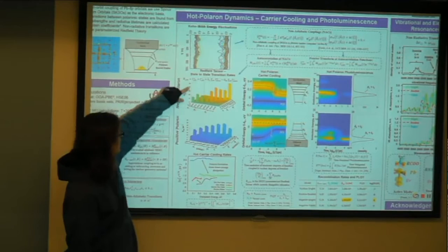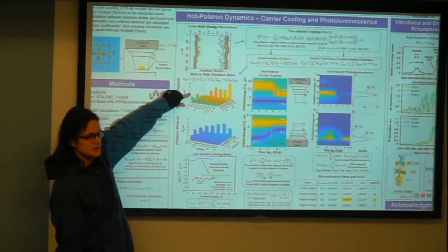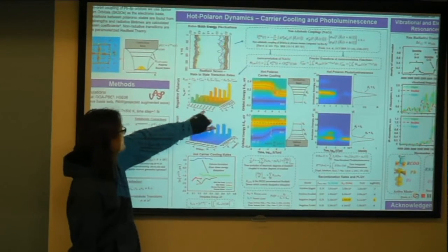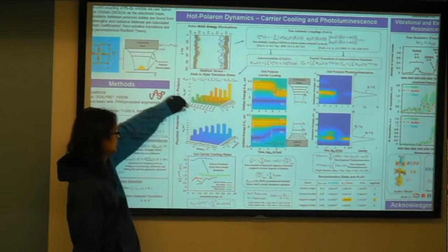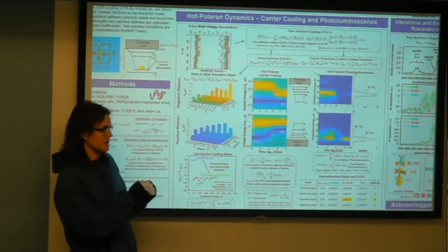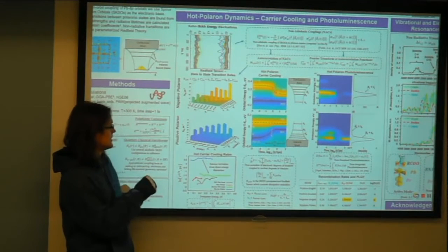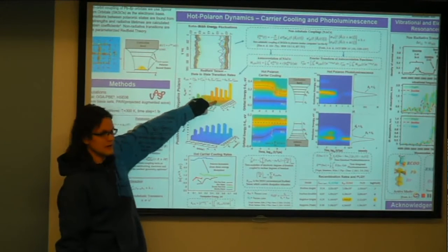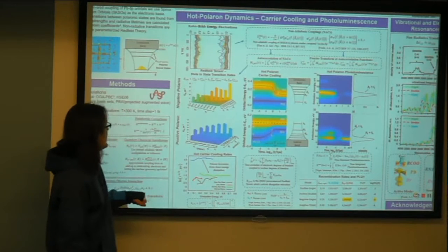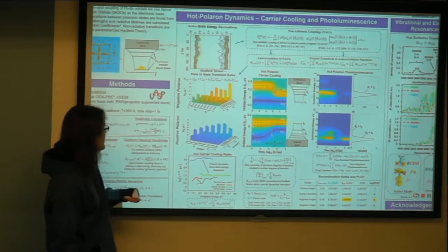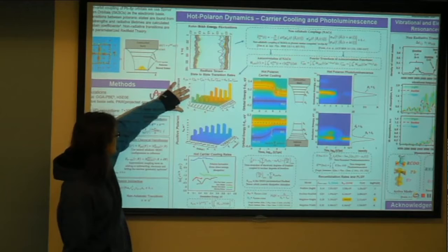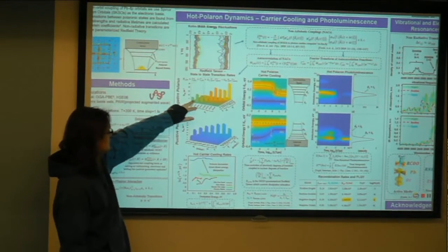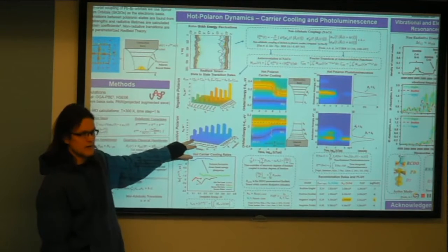So essentially, the intensity of the peak is the rate for how fast the transitions are between two different bands. And so X and Y is just state to state. So diagonals are 0, and states slightly off the diagonal should be higher intensity, and it decreases the further away you get from the main diagonal. The main takeaway from this figure is that the intensities and the width away from the main diagonal are narrower for the negative polaron compared to the positive polaron.